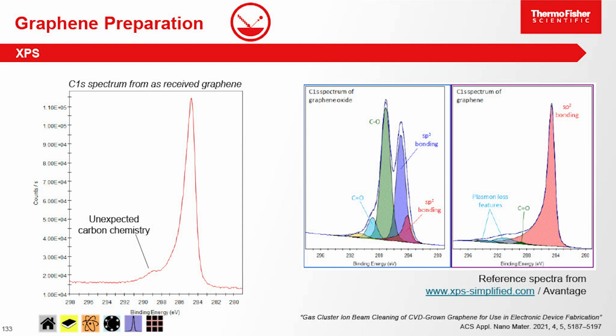So first off, we have a look at the XPS. This is the carbon spectrum from the actual sample. And it should look like this spectrum over here. These two are reference spectra from our XPS Knowledge View and the XPS-Simplified.com website. And you see this asymmetric structure. This is because graphene and graphite, which has a similar structure, is conductive. And the more metallic character you have with a conduction band and conduction electrons, the more asymmetry you get in the peak. As they become oxidized and less conductive, you lose this asymmetry and you get something that looks much more like this with the more symmetrical peaks.